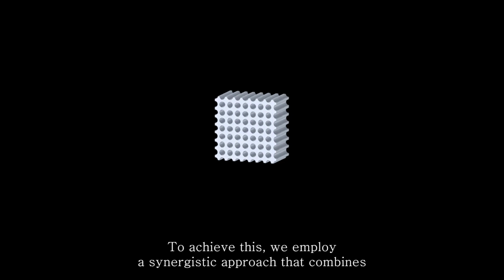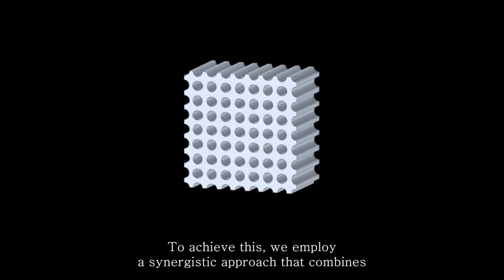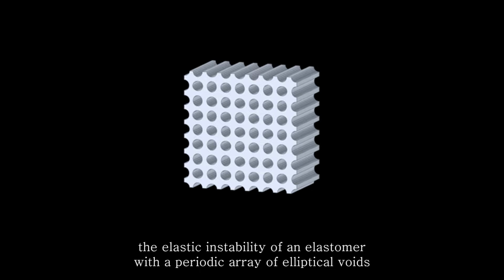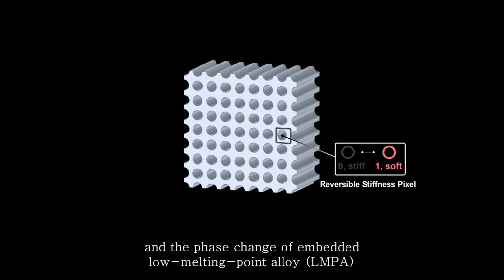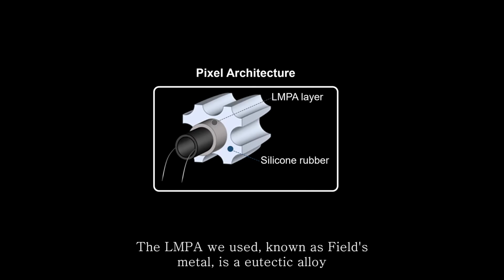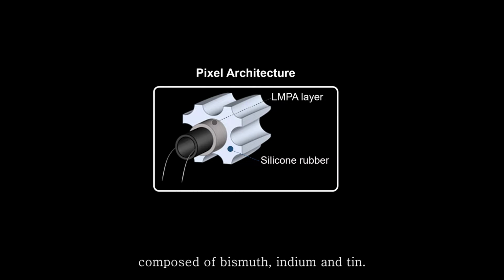To achieve this, we employ a synergistic approach that combines the elastic instability of an elastomer with a periodic array of elliptical voids and the phase change of embedded low melting point alloy, LMPA. The LMPA we used, known as Field's metal, is a eutectic alloy composed of bismuth, indium, and tin.